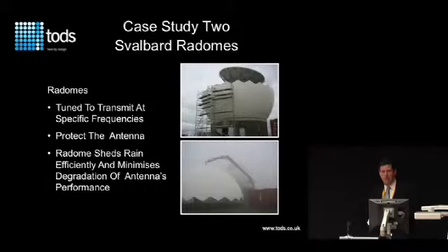We design, manufacture and install radomes, down to small radomes for submarines, up to large geodesic radomes. This is a radome, or two radomes we did for Svalbard, which is an island, I think about 600 miles off the Arctic Circle. They're tuned to transmit at specific frequencies. You tune them by the properties of the foam core, the thickness of the foam core, and the thicknesses of the skins. And they're there to protect the antenna, and also it sheds rain, snow, etc. effectively. If you get a build-up of rain or snow on an antenna, then obviously it doesn't work.